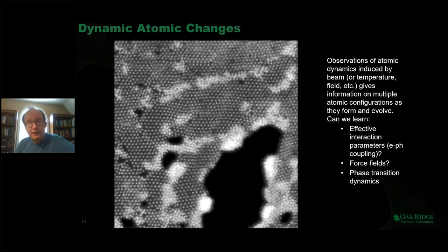But look at it from a slightly different perspective. Imagine that you are a solid state chemist. From the solid state chemist or materials science perspective, what happens here is that the electron beam, almost by magic, kicks out the sulfur atoms from the solid. The material is effectively reduced, and what you see is a chemical reaction where you form reduced molybdenum sulfide. So you see everything on the atomic level. You see how the point defects form, how the point defects aggregate into extended defects, and finally you see the nucleation of the new phase. So you literally see the chemical process on the atomic level.